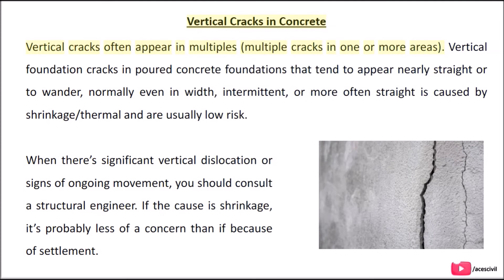Vertical cracks often appear in multiples — multiple cracks in one or more areas. Vertical foundation cracks in poured concrete that tend to appear nearly straight or to wander, normally even in width, intermittent or straight, are caused by shrinkage and thermal movement and are usually low risk. When there is significant vertical dislocation or signs of ongoing movement, you should consult a structural engineer. If the cause is shrinkage, it's probably less of a concern than if it's caused by settlement.